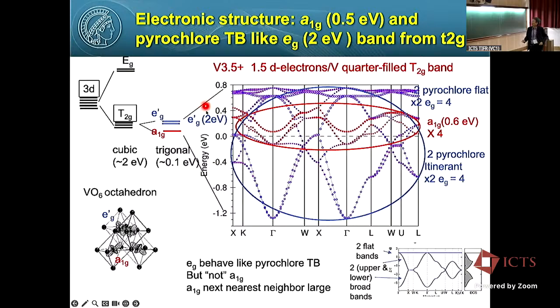And if you take a look at the band calculation, those red come from A1G character, and those blue come from EG prime character. Okay, so you see a clear separation of the character, and the EG prime looks like a tight binding pyrochlore band. You see a flat band and two, an upper and a lower, broad band for the pyrochlore tight binding band, and this blue mimics the tight binding pyrochlore band. But of course, this EG is doubly degenerate. And there is an A1G character somewhere, but they form a very narrow band, on the order of 0.5 electron volt only. But it doesn't mimic the pyrochlore band.